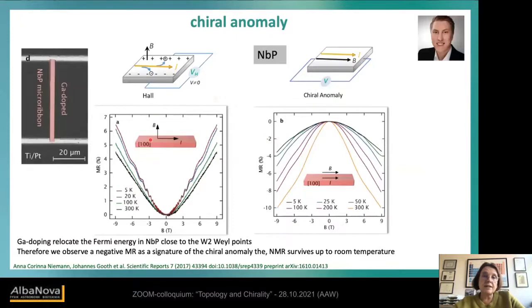So then Johannes wanted to go beyond the experiments which were predicted. He wanted to really do the chiral anomaly and the gravitational anomaly. But for this reason, we have to make sure that our measurements are reliable. So you need a very asymmetric crystal. So we have a focused-ion-beam micron ribbon of niobium phosphide here, which accidentally doped the crystal a little bit with gallium, but this was very good.